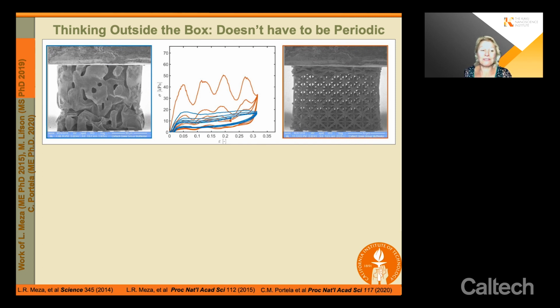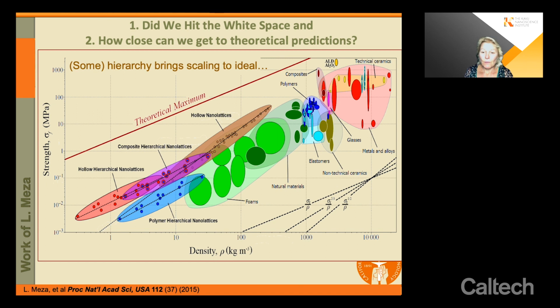We have not yet fully explored the fatigue regime, but what I can share with you is this. Actually, I even have that here. Let me go to my property space. So this is how fatigue manifests itself. When you look at this material property space, what I plotted here are guidelines for how the strength should scale with relative density for three different types of architectures. What I'm showing you here is the so-called worst type of architectures, which is stochastic. These are random architectures, like think of your yoga mat. What that tells us is that as you reduce your density by a factor of 2, your strength falls off by a factor of 4. They have this square dependence.